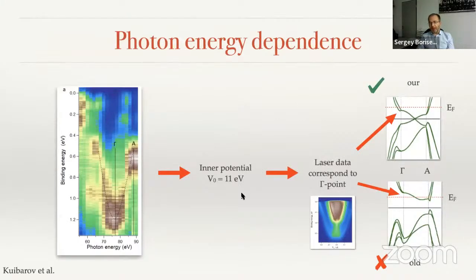Moreover, knowing the 11 eV, we know that this is mostly the gamma point. Of course, using the lower energies, you not only increase bulk sensitivity, but also your KZ resolution is a little bit worse, because you are squeezing the momentum scale along KZ, and the mixture of different features is very natural. In this case, it is very natural also because in our picture, near the gamma point there is a flat portion of the band, and there is a flat portion of the band near the A point. So actually having two components is very natural in our picture.